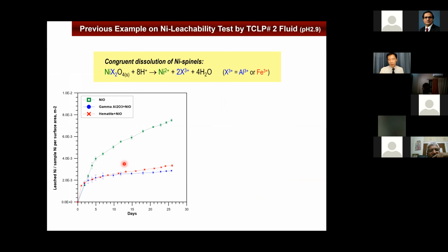And then we have this product we want to test whether it's stabilized. What we usually do is a leaching experiment. In addition to the traditional 18-hour TCLP, we have been doing all different kinds of leaching experiments. Like this one, which in fact extends to a much longer time, because our target was to compare nickel oxide and nickel spinels. Nickel oxide has already been considered very insoluble. So therefore, for most, the first 18 hours, even the first or second days.